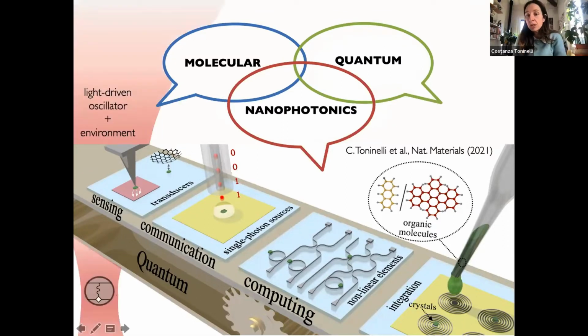To first approximation, a single molecule can be described by a two-level system with these two levels coupled by strong radiative transitions, which means that I can bring them in close proximity to suspended membranes of different materials, that I can use this molecule and its radiative transition as a transducer to read the local electric field or locally the temperature, for instance, as we will see in the rest of the talk, looking at either the emission frequency or the characteristic damping time of this oscillator, okay, this high quality oscillator.